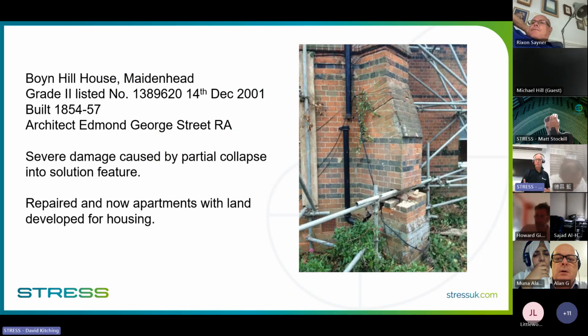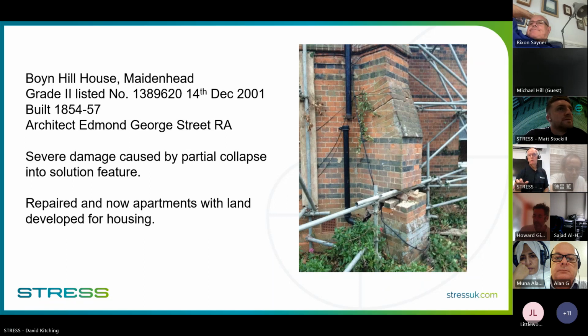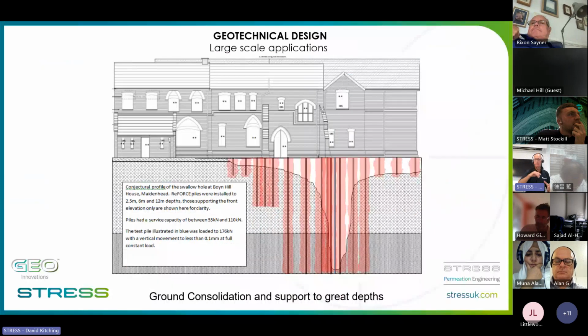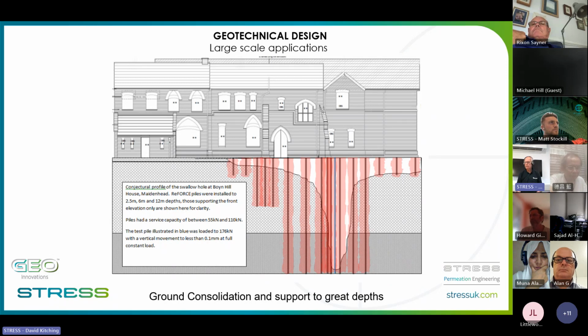So that's the sort of damage that occurred. It had a basement, and that basement really was incredibly badly cracked up. The basement sat right over the solution feature. So that was the temporary work situation when we went to site. We did all that work by piling. We even tried to do filling of the solution feature with a cementitious grout. It was something that the client asked us to do. If we could fill it, would we try it?